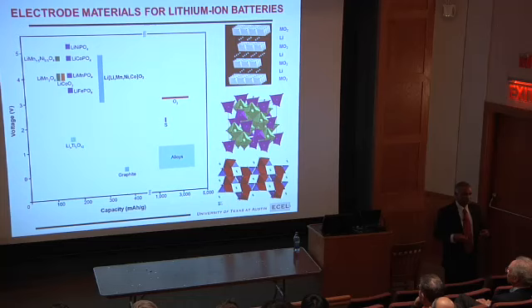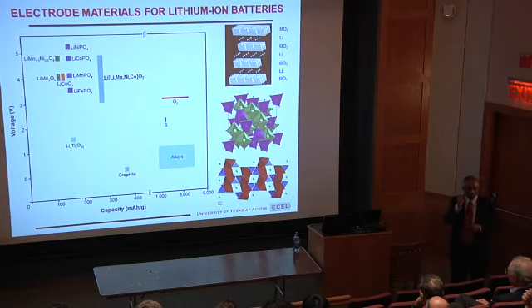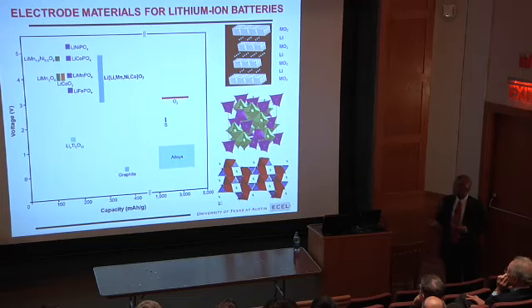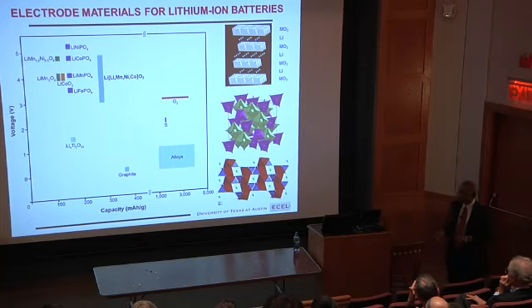So what we should do, even though among all of these, iron is the cheapest and most environmentally benign, manganese is good too. To overcome this problem, I have to make small nanoparticles, and then I have to coat them with carbon uniformly, so processing cost goes up, and also you have to make it consistently the same kind of material, quality control. So the cost of LiFePO4 is much more than LiMn2O4. So cost is a big issue. Raw material may be cheap, but your process has to be less expensive to be cost competitive.